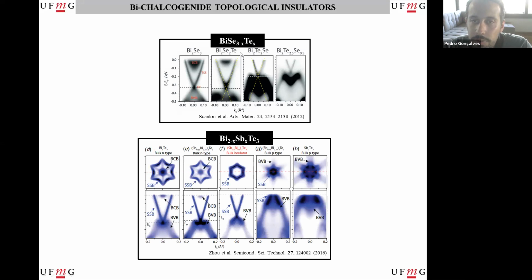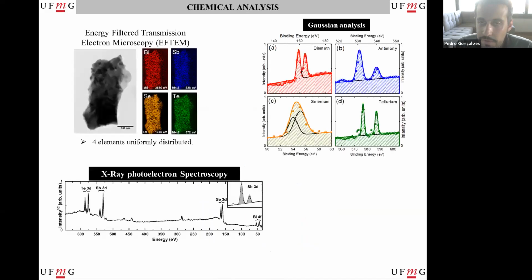Yeah, the thing is that we can find a lot of works in the literature about when we have 3 elements instead of 4. Here we can see the effect of selenium and tellurium, and here of bismuth and antimony, and they have opposite effects. When one of them moves the surface states, the other one moves the valence band. We are trying to find a specific doping. If you look here at bismuth selenide, a topological insulator should have the states crossing the Fermi level. For example, here is an actual topological insulator. Here is not, because you have the conduction band on the Fermi level. Here is also not, and we're using all these 4 elements to have a surface where we can have